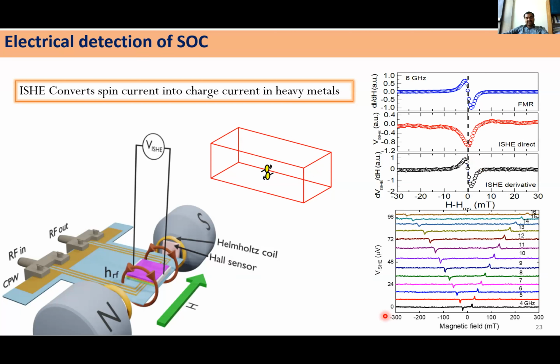signal. And to make sure that it is truly because of the inverse spin Hall voltage, as you can see, we have varied the magnetic field in both directions, and you can clearly see that as we increase the magnetic field, the frequency at which this V_ISH, that inverse spin Hall voltage, is found is increasing, and also the polarity of this signal has changed when we change the magnetic field direction. That gives us a hint that it is because of ISH.